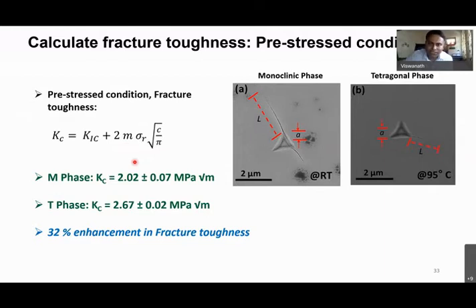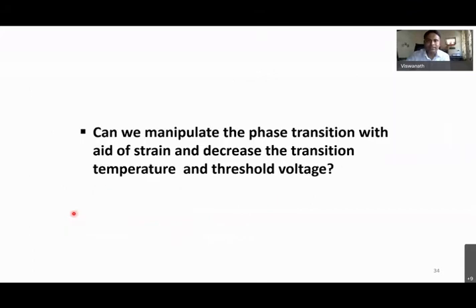So if I add this residual stress of 0.95 gigapascal, then we calculate reasonably expected values. For the monoclinic phase, we are getting something around 2 megapascal meter power 1/2, and for the tetragonal phase, we are getting 2.67. So there is almost around a 30% enhancement in the fracture toughness, which may be explained by taking the elastic modulus, or otherwise the surface energies of the monoclinic and tetragonal phases.